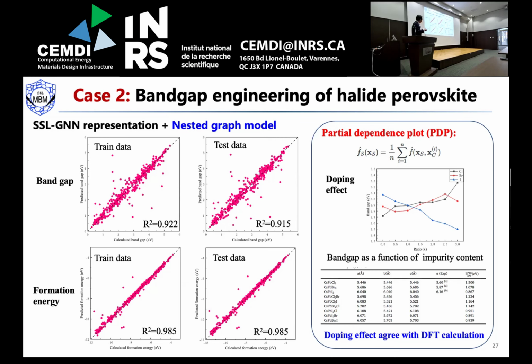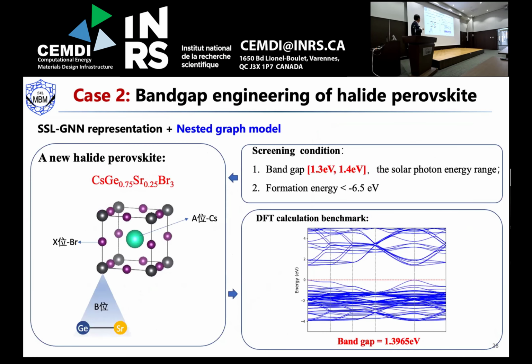And we also do the DFT calculation. We show that once you add Br into these crystals, you will find the band gap decrease. This is consistent with our prediction. So based on this model, we can do some prediction. For example, if you want the band gap to range from 1.3 to 1.4 eV, which is the solar photon energy range, and also we want the formation energy to be less than minus 6.5 eV, then we use our model to predict the new material. For these materials, we do the DFT calculation, and we found the band gap is 1.39 eV, very close to our requirement.